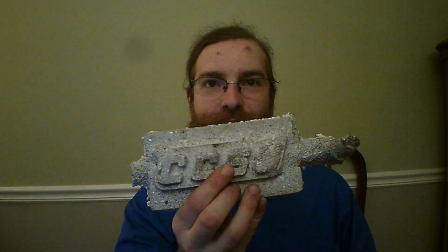Also, I had a bit of collapsing in one of the letters. That was from when the pattern was drawn out of the mold. The sand itself partially bonded to the U as it was drawn out, and so the remainder, yeah. These marks here are from when I put this in a vise to show that castings are more prone to brittle failure than any other types of metal you may have worked with so far.